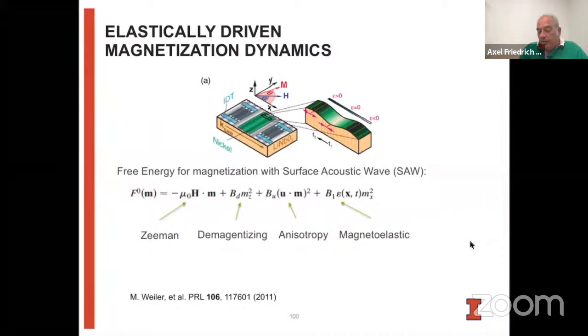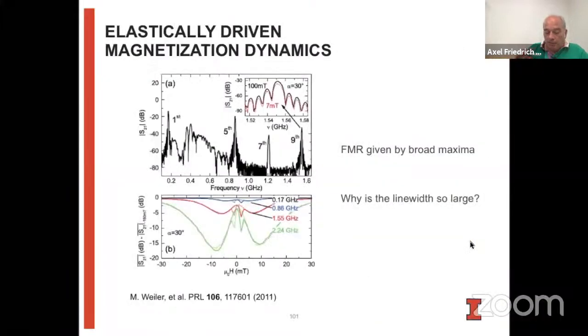So essentially, there has been a lot of very interesting work, again, by Matthias Weiler and others, where they integrated nickel into a surface acoustic wave device based on lithium niobate. By exciting surface acoustic waves, you strain the nickel film on top. And so the magnetoelastic coupling will act as an additional RF effective magnetic field that can excite magnetization dynamics. And so you can look at elastically driven magnetization dynamics.